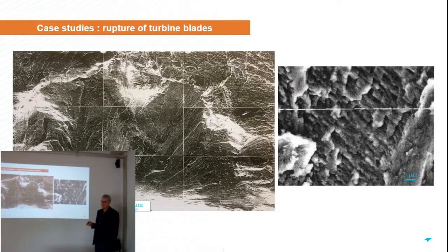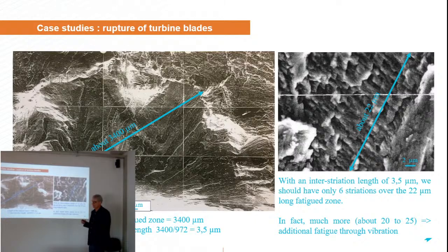And when we did the analysis of this, we have a higher magnification image here of the fracture zone, where you can see mostly the zone where the crack propagates prior to the final fracture, which is here. And when we do the measurement here, this zone of crack propagation is about this length, and considering the number of cycles, which was 972, we can determine, using the measurement of the fatigue zone, what we call the interstriation distance, characteristic of each cycle. And we found something like 3.5 micrometers.